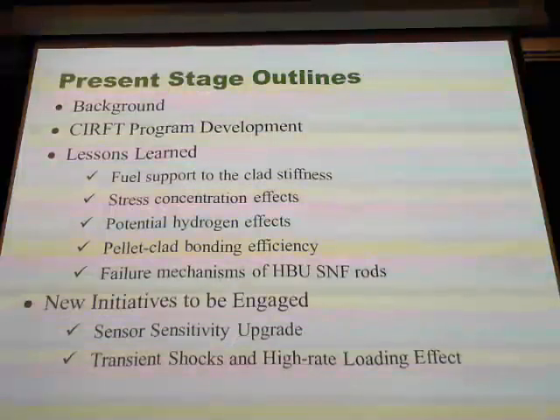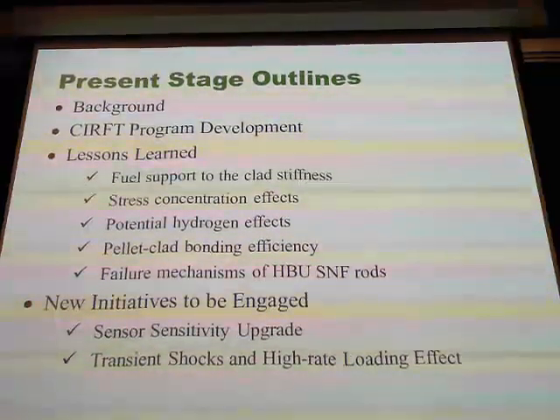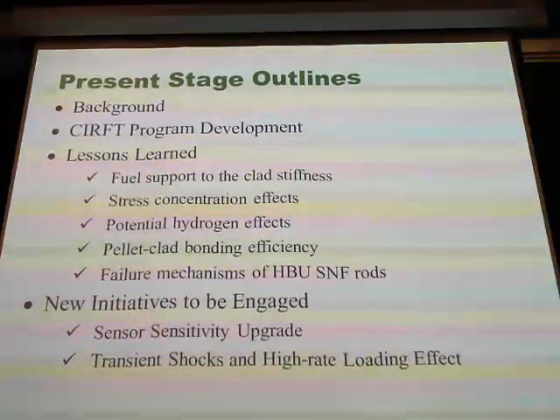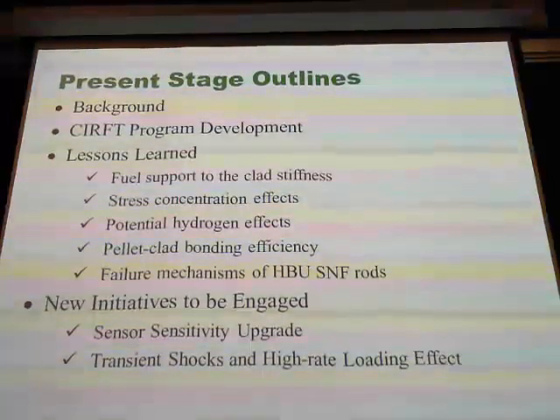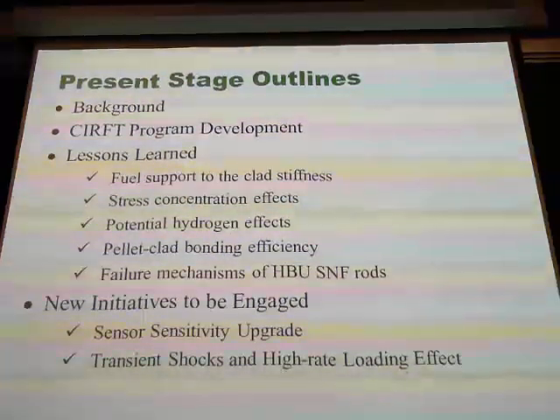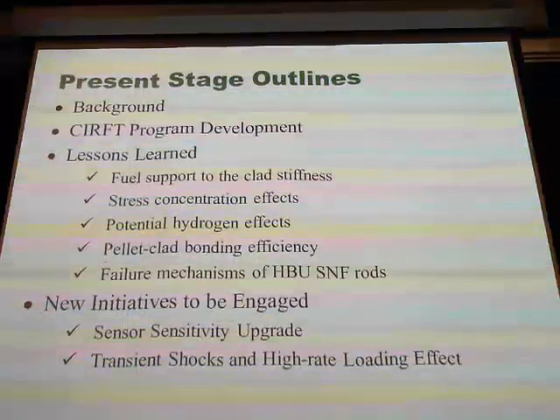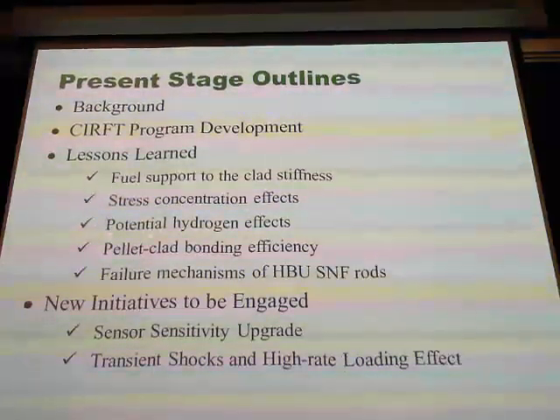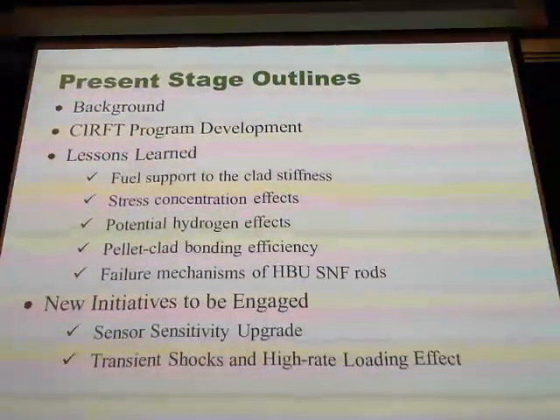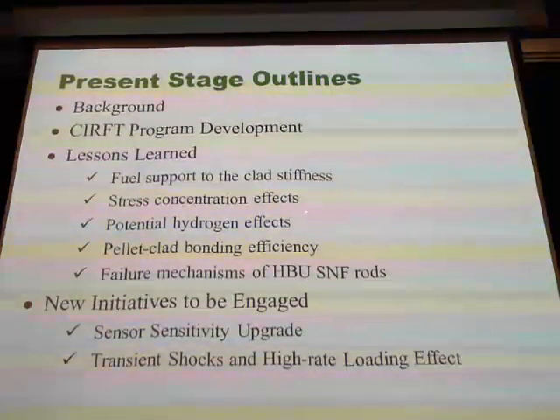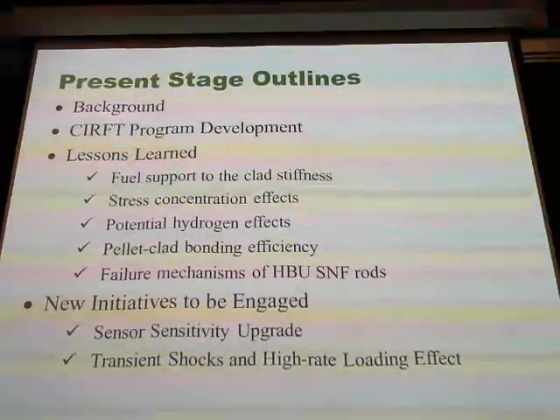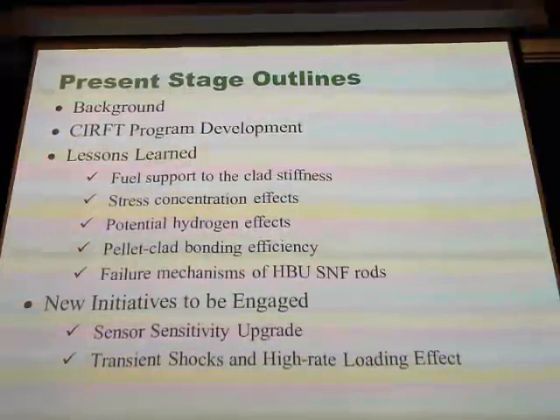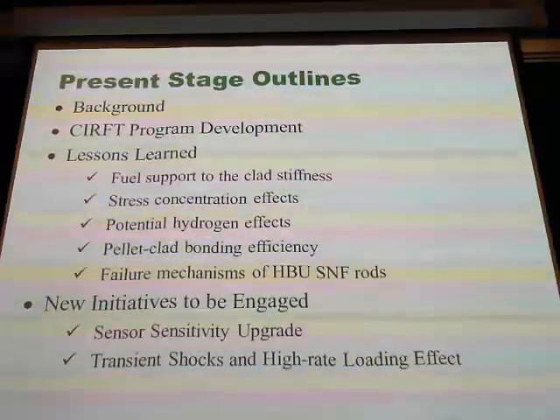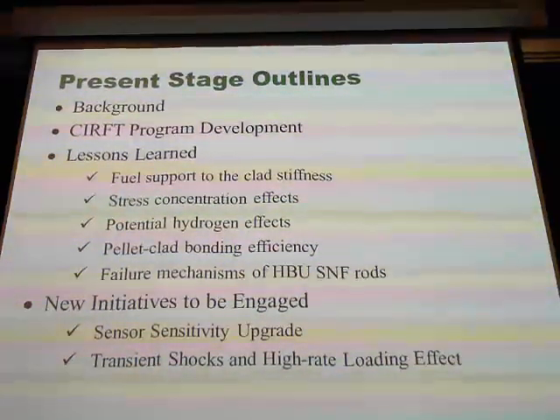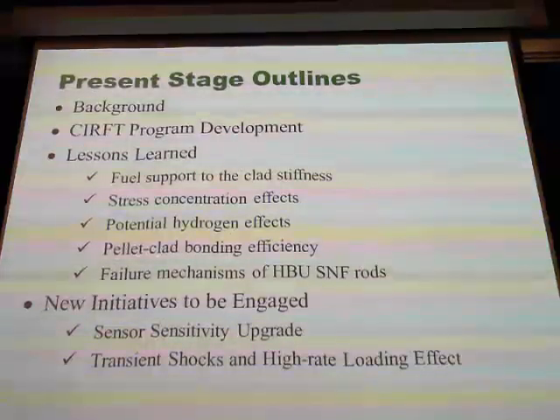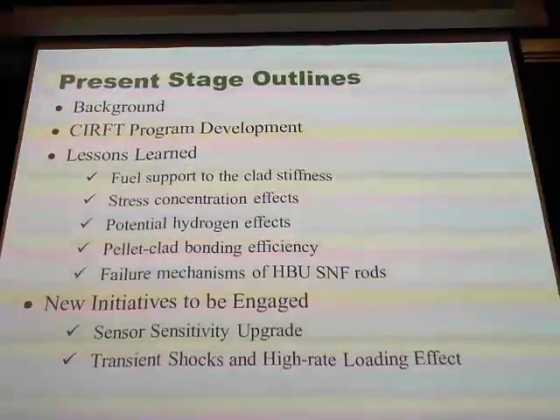And stress concentration. This is a side effect. When you have a fuel, but not a single fuel, it's a segmented fuel pattern, you generate stress concentration. And how much stress concentration impacts the lifetime is the second question. And then follow along basically with inherited material properties from aging history for the hydrogen content, so-called hydride in this case. And pellet-clad bonding efficiency.